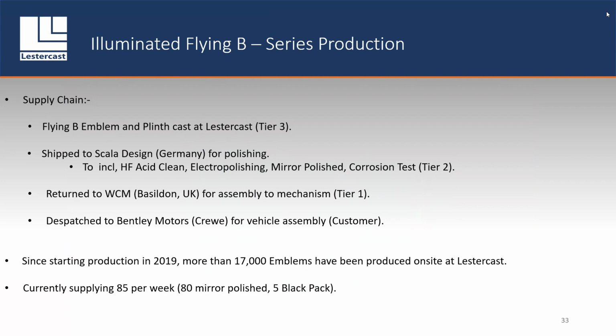We then ship the parts to Germany to a company called Scala Design, who hand polish, literally every part hand polished. It also includes a hydrofluoric acid cleaning process, which removes any impurities from that cast surface. There's an electropolishing requirement for the illumination. So the whole of the part is electropolished so that we can get the EP onto the inside of the wings. It's then mirror polished, and then they're 100% corrosion tested because the customer doesn't want to see the emblem going rusty. And these cars go to some extreme conditions, hot and sandy conditions in America in particular.